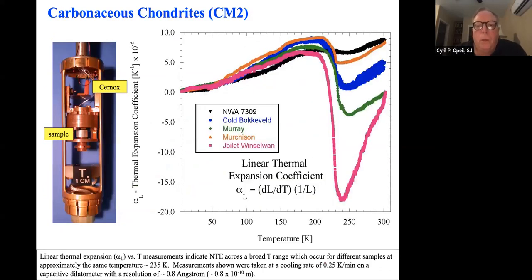Now, this is something that was very unusual when I measured these materials. The Bokkeveld meteorite was a piece of a Vatican meteorite that Guy Consolmagno gave me and said, maybe measure this. There was really no expectation about doing linear thermal expansion, but I thought, well, I have the technique, I may as well use it, see what happens. As you can see, going from low temperature to higher temperature, up until about 200 Kelvin, it's expanding like a normal material would expand.